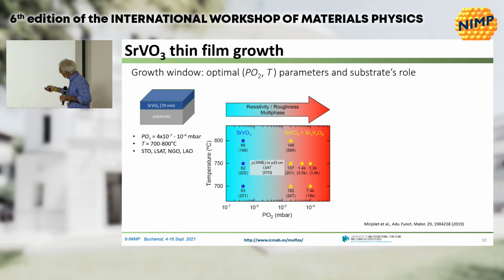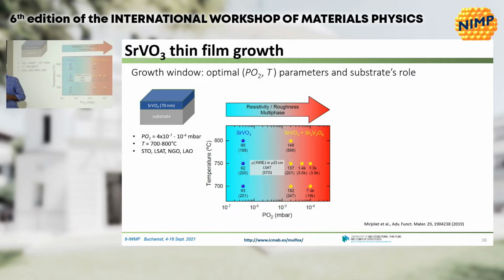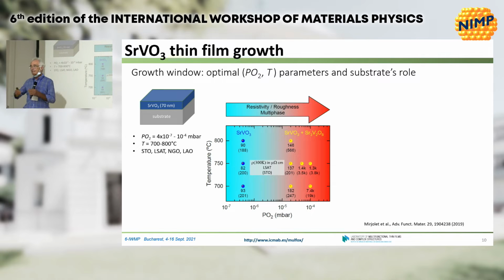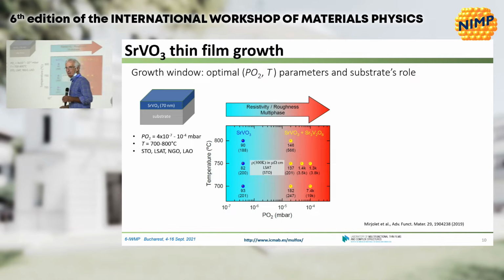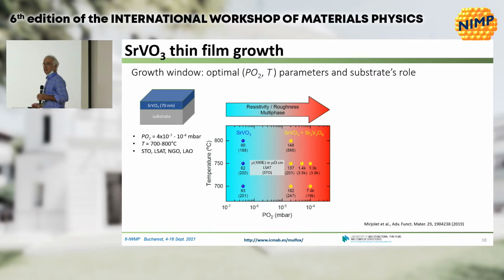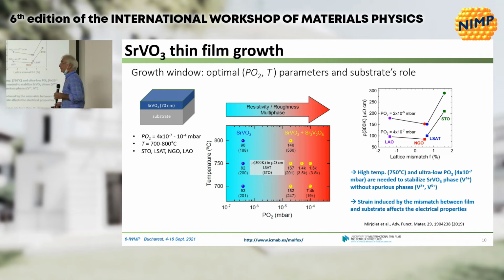So you need this high temperature and low pressure, and in terms of PLD growth, this is critical, because when you go to low pressure, then the energy of the plasma is very high. That means that you are creating a lot of point defects in the film, and the residual resistivity of your film is going to be larger. So you need a low pressure, but at the same time, you need to reduce the number of point defects in the film. And we overcome this difficulty using an auxiliary argon gas in the chamber at the lowest pressure. We put in a bit of argon, and then you reduce the energy of the plasma, you reduce the residual resistivity, and you can get the optimal films.